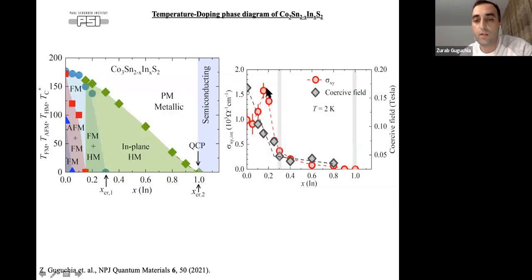At the moment, we don't fully understand the peak here, why the Hall effect has a peak, but it could be related to some kind of charge transfer between these different magnetic regions. Maybe we have more charges in the ferromagnetic state coming from the antiferromagnetic state, and then the Hall effect would increase because the density of electrons would increase in the ferromagnetic regions. But this is something that we need to work more on to understand. But at least we can have very efficient tuning of the magnetic competition by indium doping.